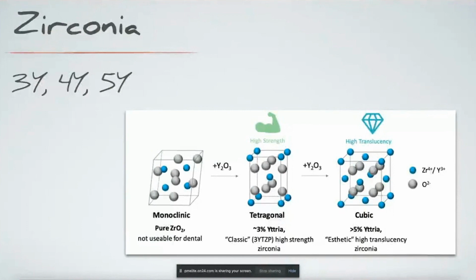If we look at pure zirconium oxide, they're going to call it here the monoclinic oxide. This is just pure zirconia, very, very strong, but not really usable in dental clinics whatsoever. Once we start incorporating some yttria, and here you're going to see the tetragonal kind, 3% yttria, this is going to be the high-strength BruxZir type of zirconia. Okay, so it's going to be what you had when it first came out, even when Glidewell released it years ago. Super hard, really, really opaque though.